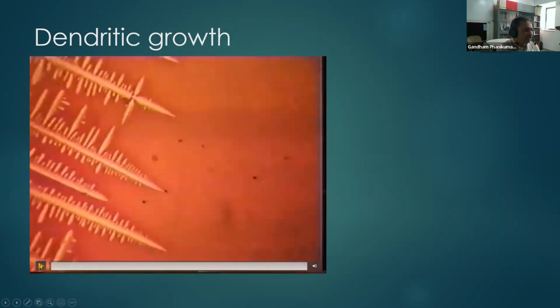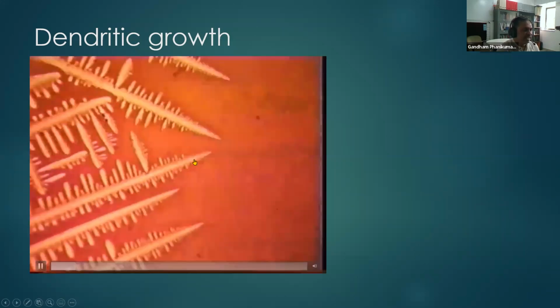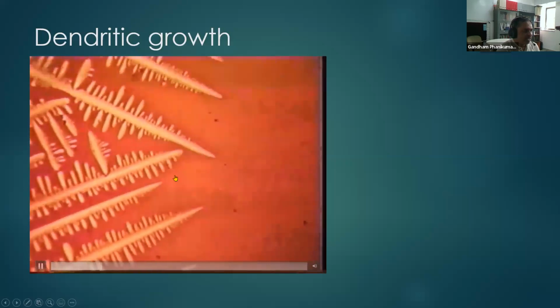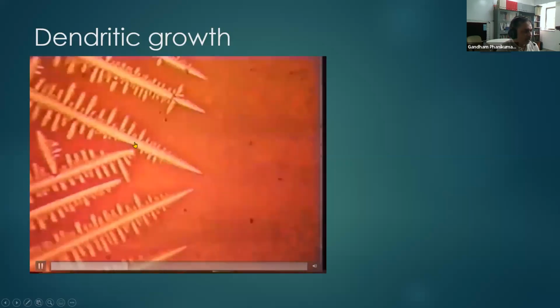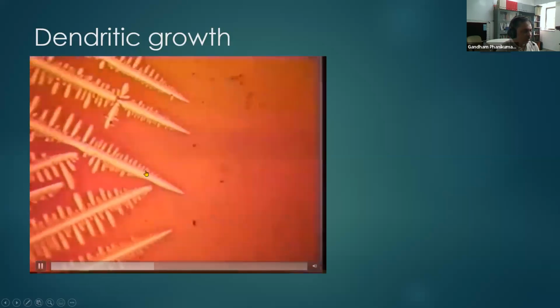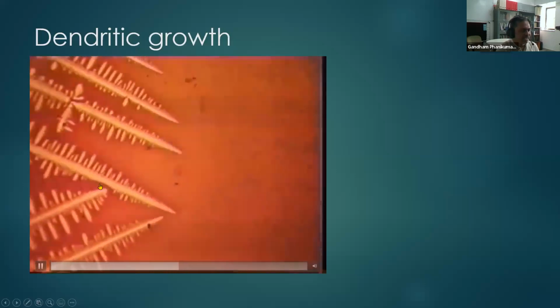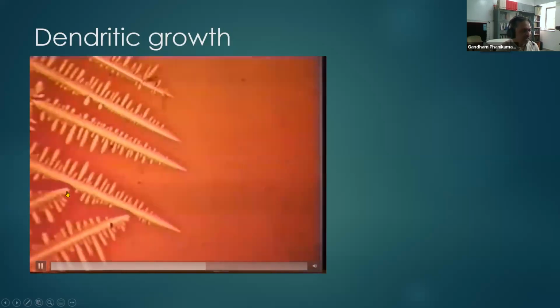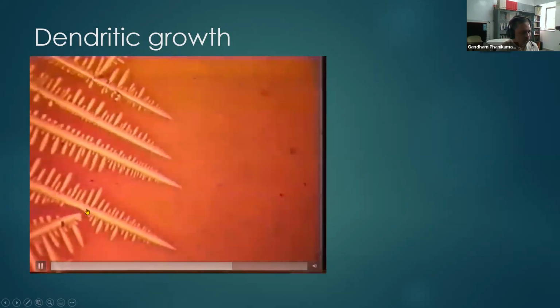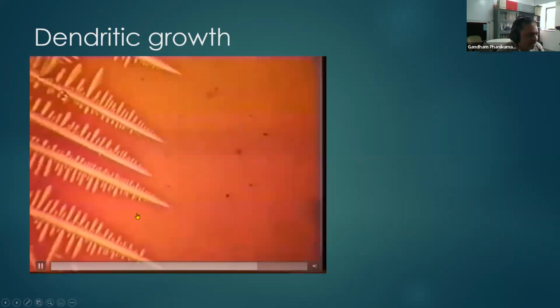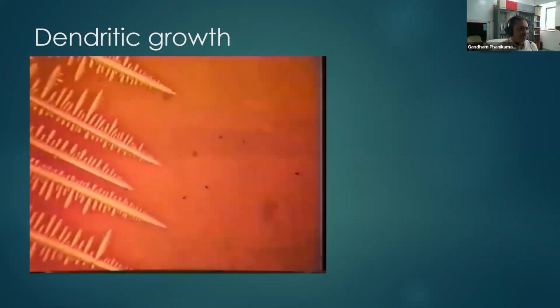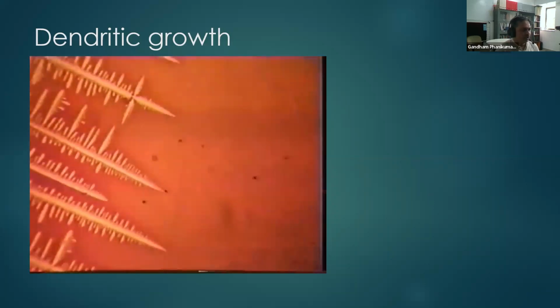Something I want you to pay attention to is that there's latent heat released by the growing solid, because of which the side arms cannot grow, and elsewhere it will grow. So wherever the interaction between the solids happens, there is latent heat released and the side arms don't grow. A lot of the patterns growing in solidification can be understood once we know how these interactions happen due to release of heat during solidification pattern formation.